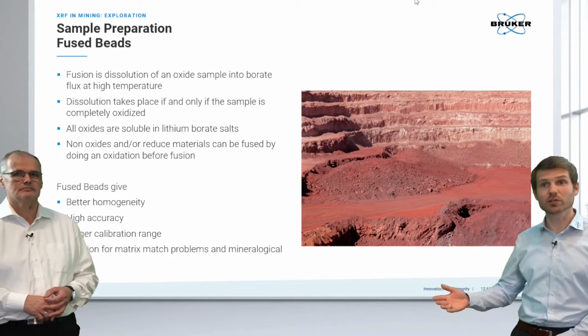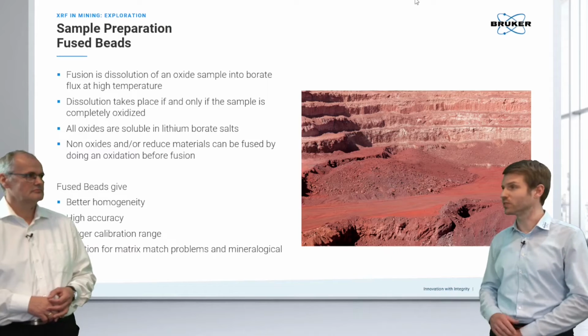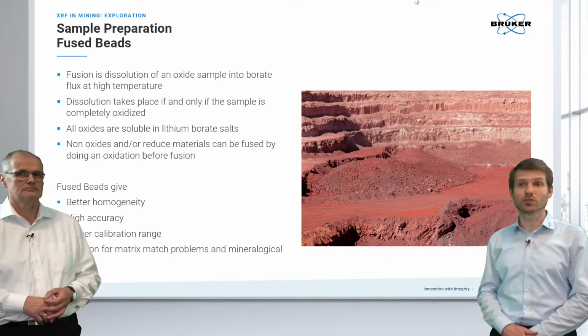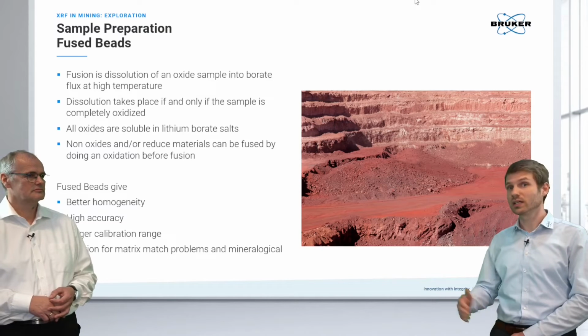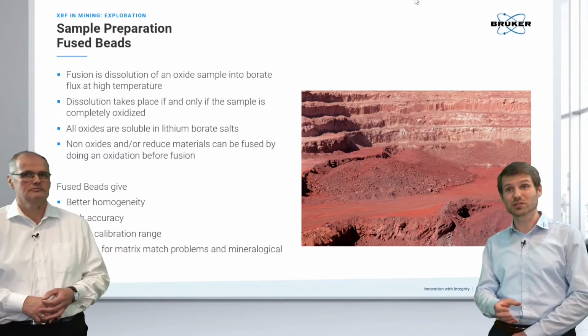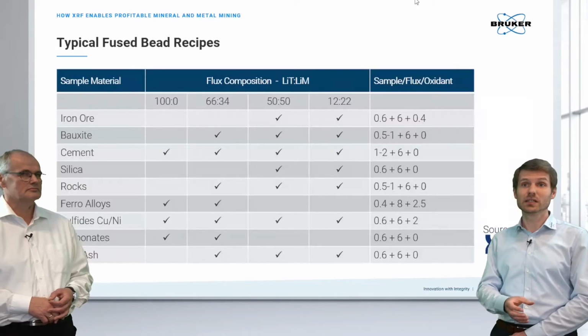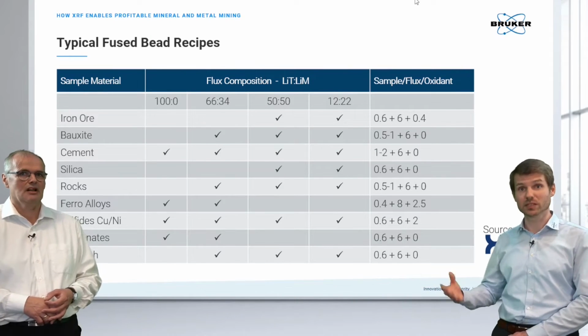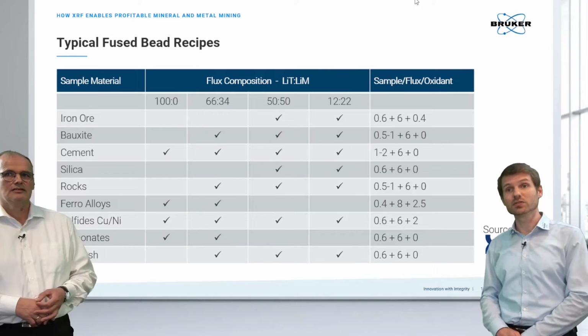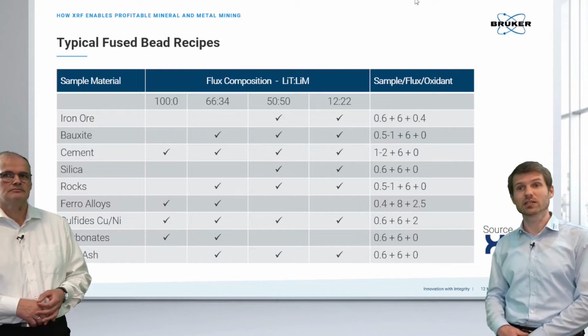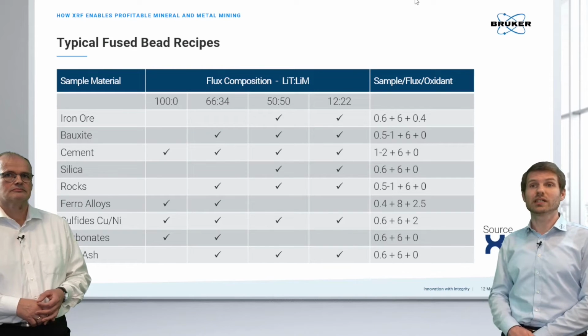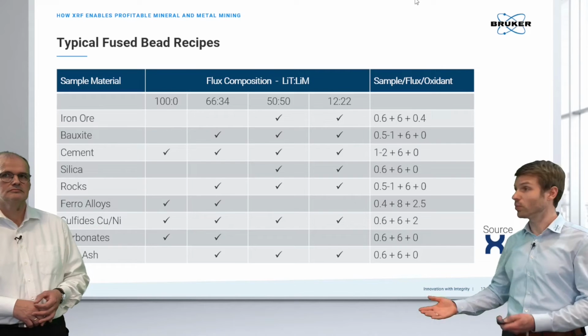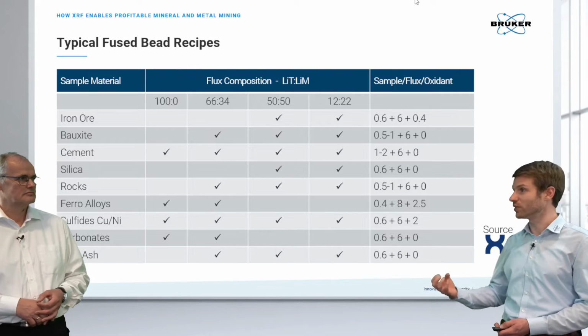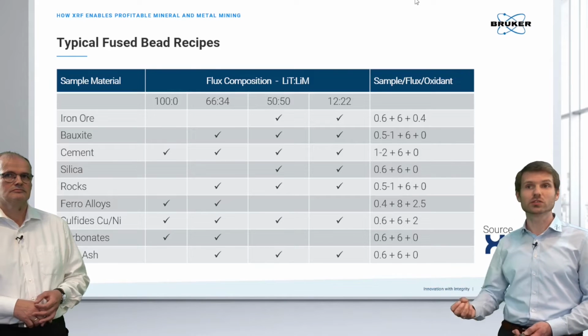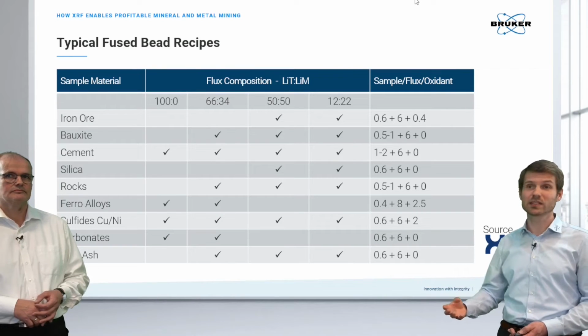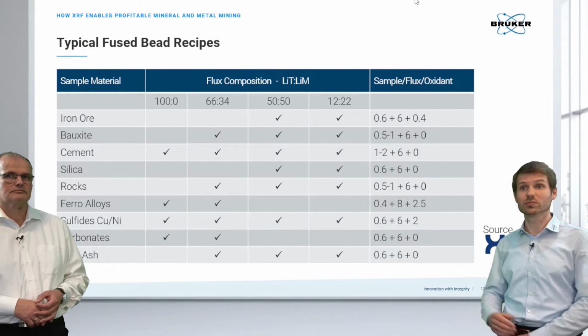Yeah. So maybe to add to that very briefly, there's of course always a bit of a sweet spot for the two types of preparation, be it pressed pellet or fused bead, and that's something we can always help you with. So for instance, when you're really looking at the traces, then the dilution rate that you're dealing with in fused beads might be a problem. Here we have some examples for different fused recipes, and Kai will go into that maybe in a few seconds. But then you can also imagine that there are some ores, like copper ores for example, which have a relatively high concentration of the element of interest, copper, but you want to know that relatively precisely, and you're dealing with a very complex and diverse mineralogy which causes matrix effects. So then fused bead is definitely the way to go.